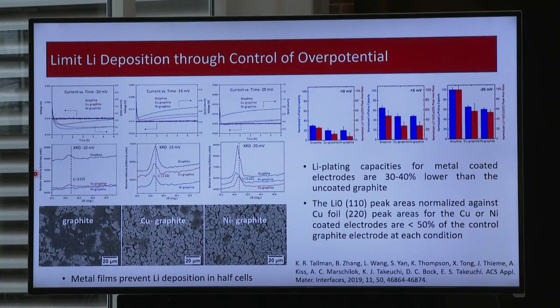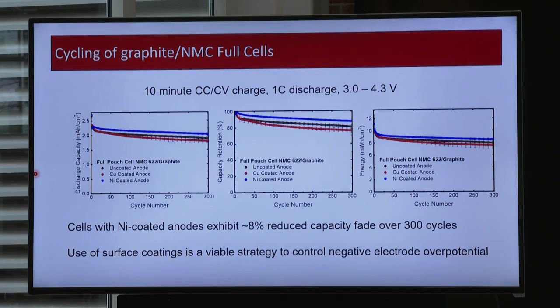So we did some fundamental studies really looking at lithium deposition and quantifying it through X-ray diffraction, scanning electron microscopy, and measuring the capacity, or the coulombs, driven below zero lithium potential. And sure enough, for the electrodes that were either copper-coated or nickel-coated, quantitatively the amount of lithium deposited was much, much less compared to the uncoated graphite. So this was looking quite promising.